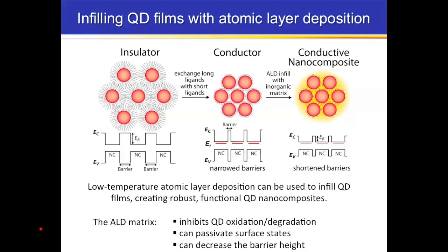Okay. And by doing that, we achieve a number of things. The first thing is that we get environmental stability. So the ALD layer acts as a great gas diffusion barrier. It stops oxidation, as I'll show. It also stops internal diffusion within the film, and so it prevents the dots from sintering together at higher temperatures.